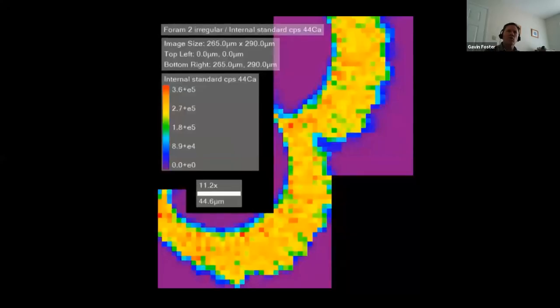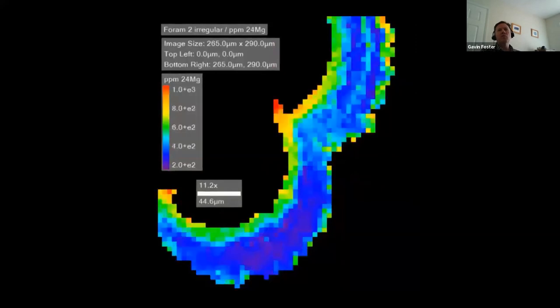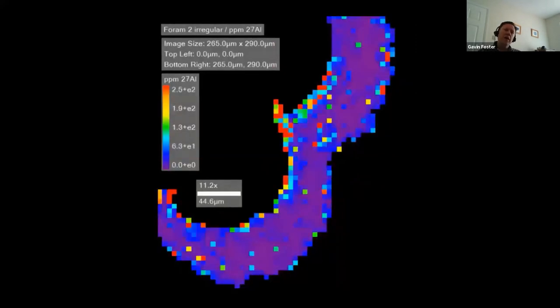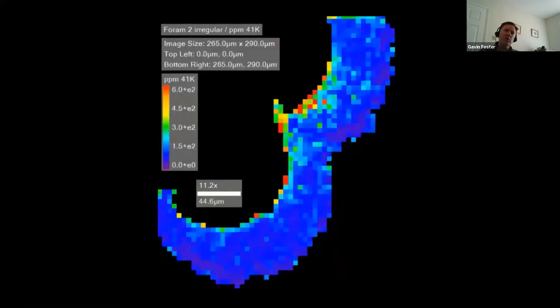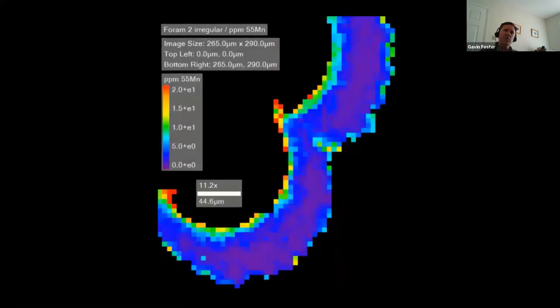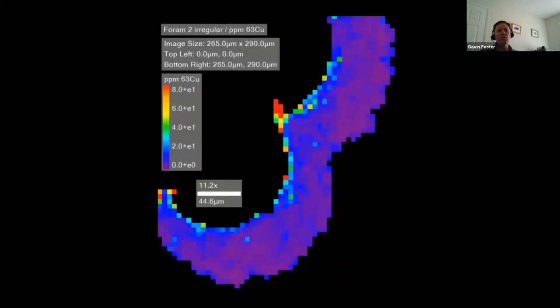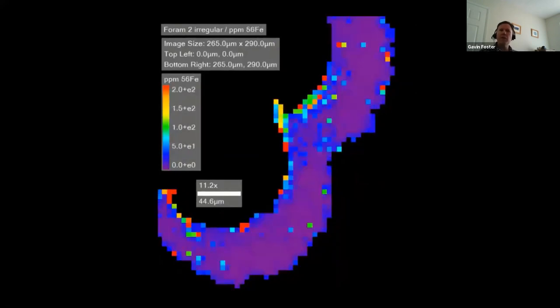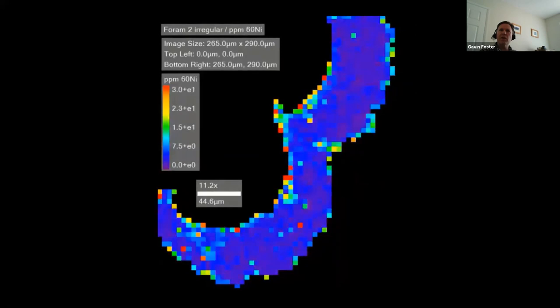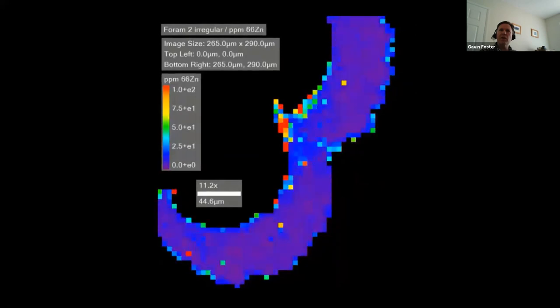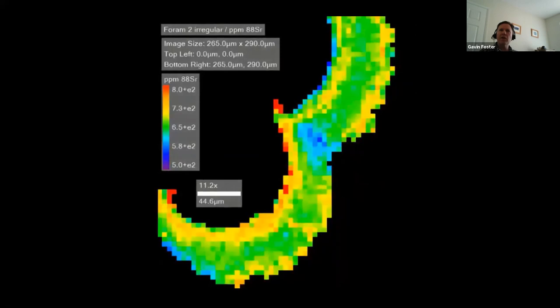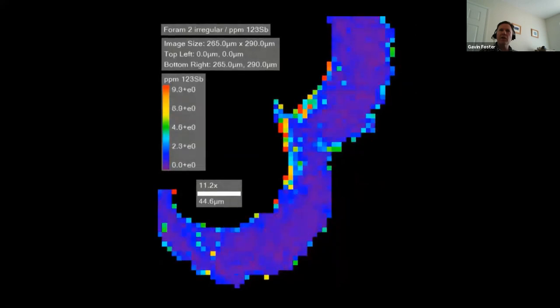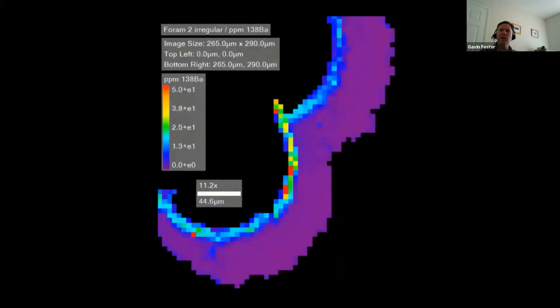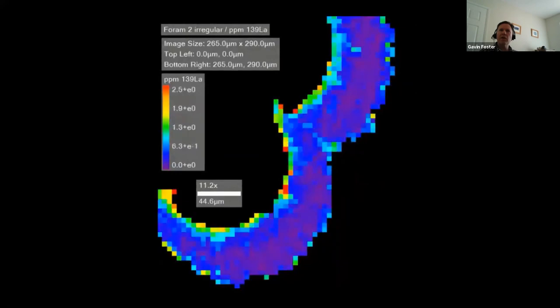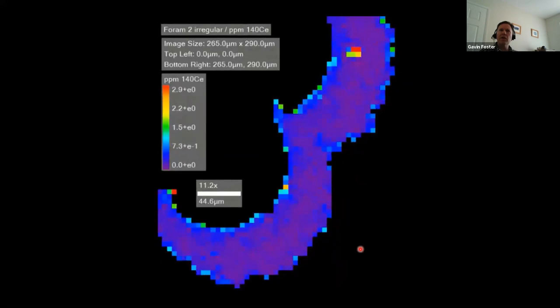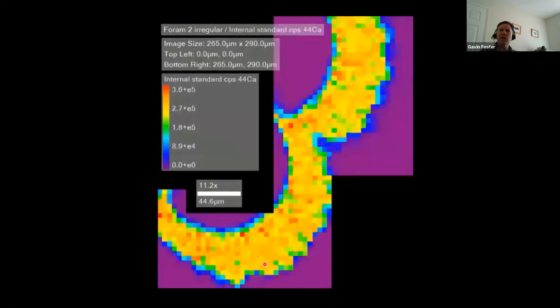So here, it's going to cycle through a bunch of maps of all different types of elements. And I think what has really impressed us with these images is that you get elemental information on all the elements in that spectra. So you're getting information on elements that you wouldn't have even looked at, which I think is really useful. But the elements that we are interested in are nicely represented, and we start to see some interesting features, like here in the barium, lanthanum, cerium, lead. You've got this large lead spike on the outside.